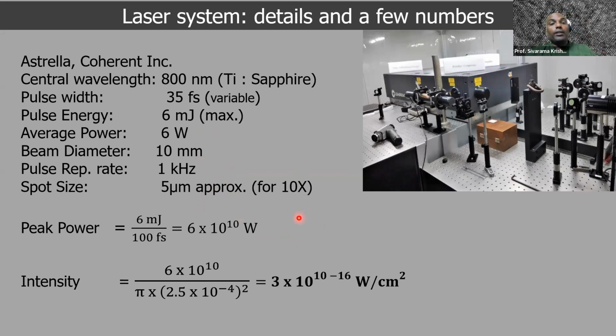The peak power, which is essentially the energy per unit time, and the maximum of the energy per unit time here, although each laser pulse seems quite delicate, just 6 millijoules, because these are sub 100 femtosecond pulses, it is huge. We have about 60 gigawatts of peak power in every laser pulse. Of course, this is only the peak, but even this has a lot of significance. Why? Because we can focus this down to small spot sizes, and intensity, which is essentially the power per unit area incident on any sample, can be varied very nicely between about 10 to the 10 to 10 to the 16 watts per square centimeter.